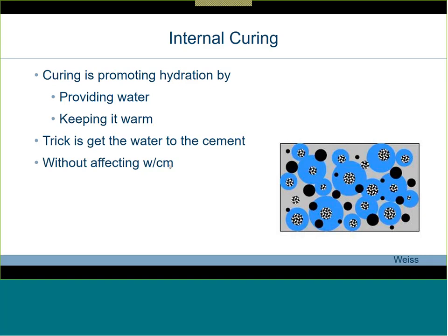And if you've got a low water cement ratio system that's consuming all of the water in the mixture, you can actually get some desiccation towards the bottom of the slab, and conventional curing doesn't change that. Internal curing is the idea of mixing some little reservoirs full of water. It doesn't affect the water cement ratio, but it does get sucked out of these reservoirs later on and help to cure the concrete. Therefore, there's better uniformity. The blue in the image is the affected curing benefit from these lightweight particles. And it's more uniform than doing just a surface treatment.